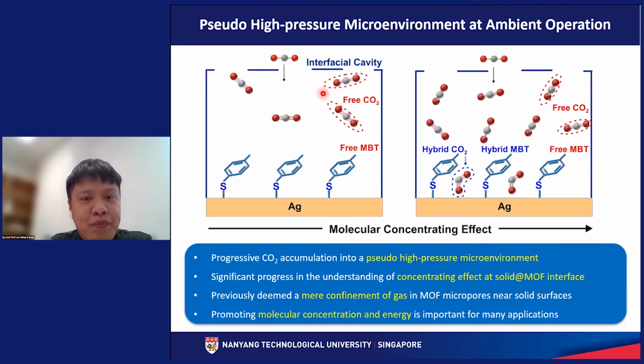So at this stage, CO2 molecule is not forced very near to the surface, and there is negligible steric repulsion, and therefore they will exist as linear geometry. But as we continuously concentrate CO2 molecules into the interfacial cavity, right now we are forcing carbon dioxide very near to our silver MBT surface. This will cause steric repulsion, and this will cause the formation of geometrically bent carbon dioxide molecule. So in other words, progressive carbon dioxide accumulation into a pseudo high pressure microenvironment can be seen from our result.